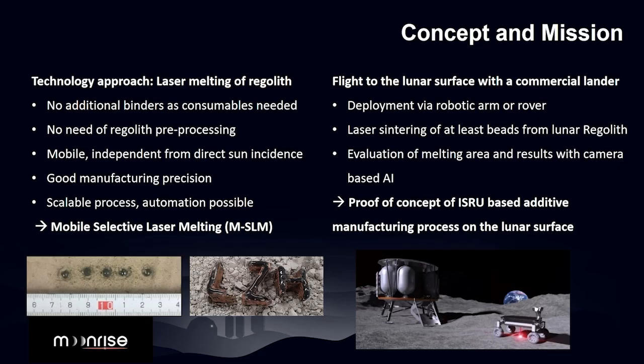The technological approach is that we use a laser for melting and sintering the lunar regolith directly on site, which has the advantages that it needs no additional binders and consumables. We also need no pre-processing of the lunar regolith. We can directly work on the lunar surface. The technology can be made mobile. It is independent from direct sunlight. And we have a good manufacturing precision. And this process is scalable and highly automatable, which is good for one of the main purposes of de-dusting large areas on the lunar surface and support of lunar infrastructures.